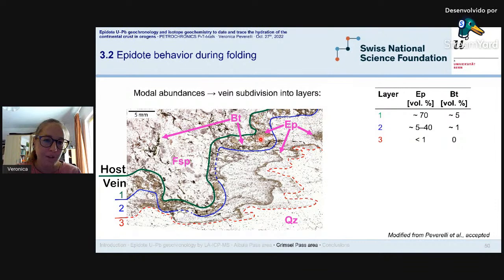So we have layer 1, which is dominated by epidote, and in which maybe you cannot see it, but you can also find some elongate epidote grains that suggest that this layer formed during veining. Then you have layer 2, in which the modal abundances of epidote are very variable, and the spatial distribution of epidote and quartz define a microfold. When we move away from this epidote-rich band, we go towards lower modal abundances of epidote. And finally, we have layer 3, which is almost entirely made of quartz.